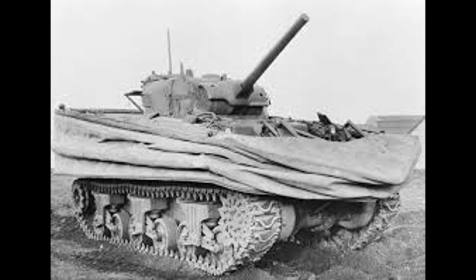And by March 1943, as the first Valentine DD tanks were being delivered for training, the leaking problem was getting worse. During sea trials at Stokes Bay near Gosport, tanks that had passed their lake tests would start taking on water in the choppier conditions of the Solent. The additional stress from wave action was opening up microfractures in welds that had looked perfect in still water. Crews were having to run their bilge pumps continuously during swimming exercises, and some tanks were barely staying afloat.